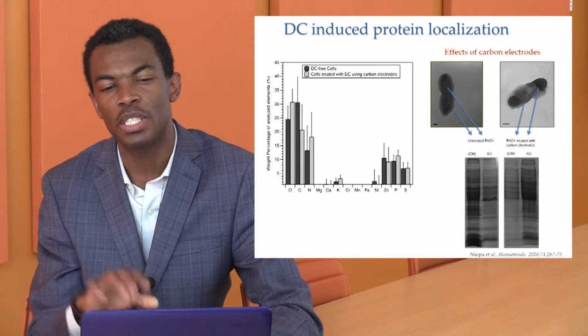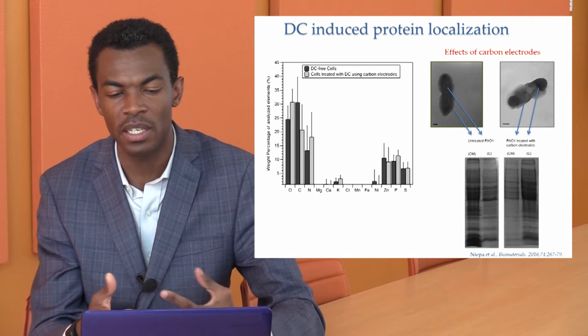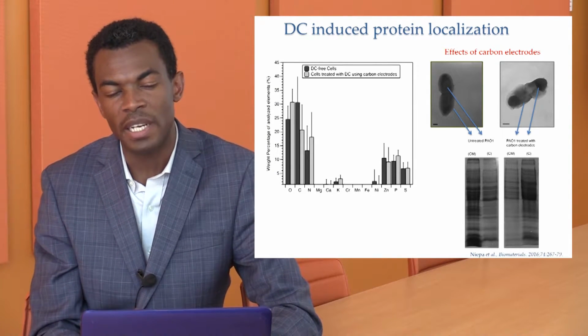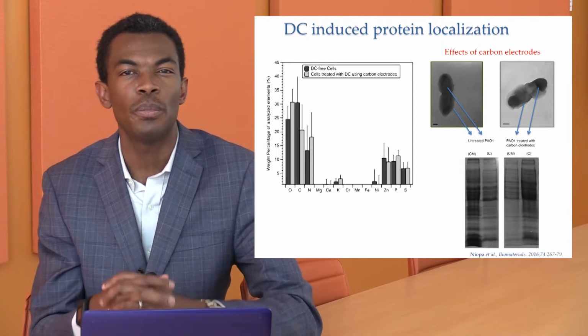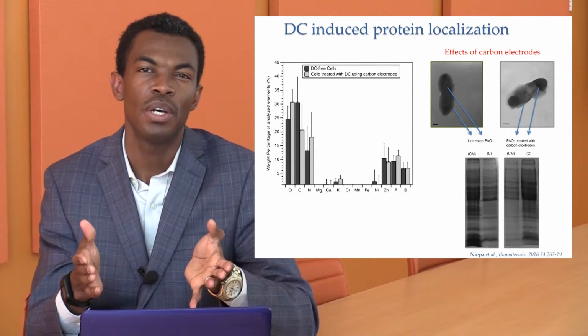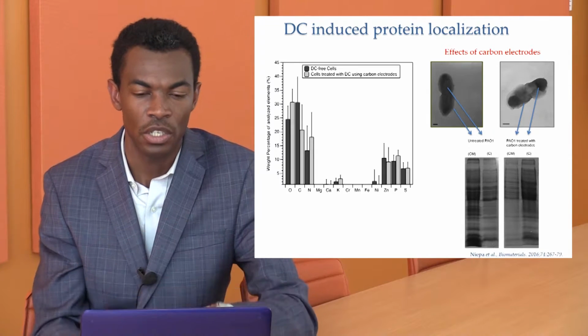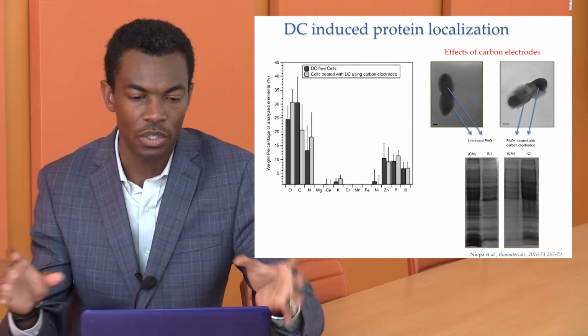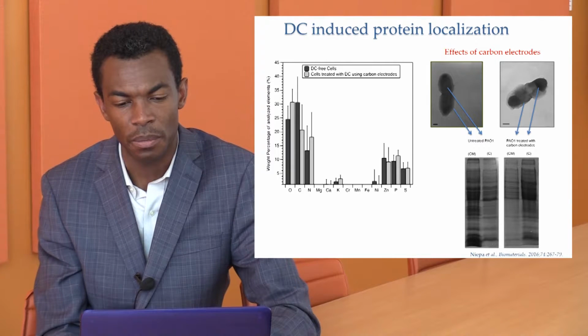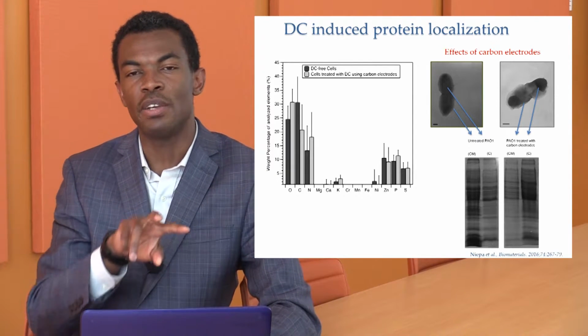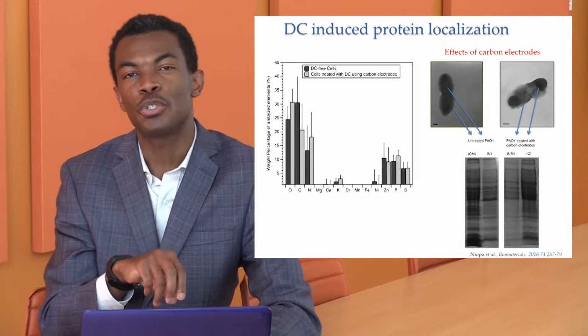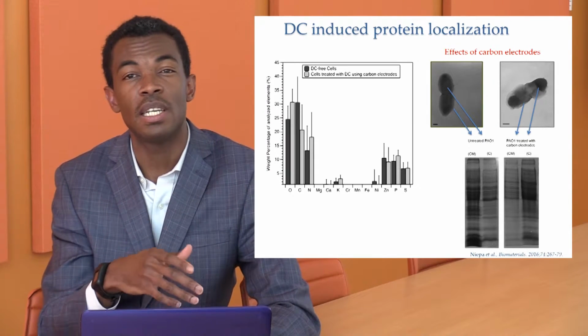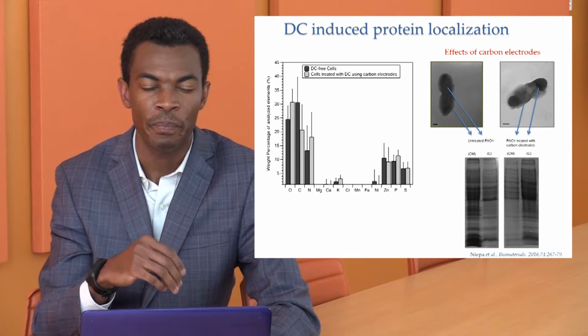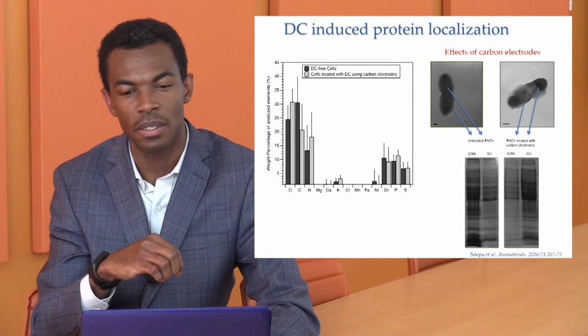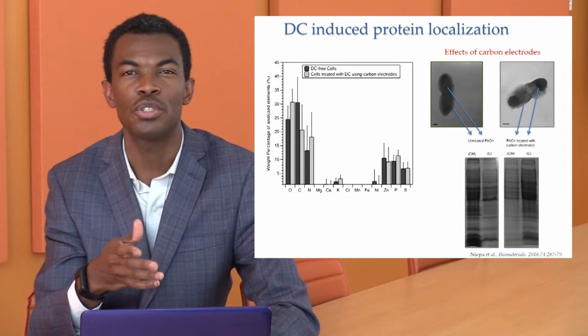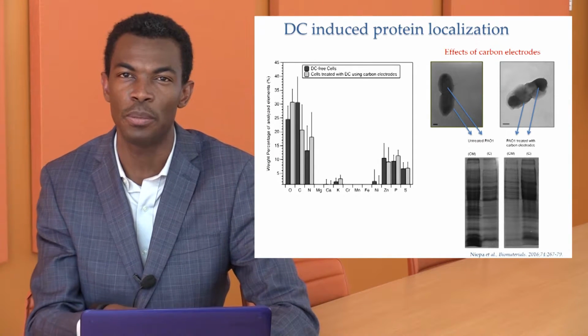So we're trying to confirm this fact, and we did perform some analysis just by quantifying the number of proteins that the cells have on the cell membrane compared to the inside, in both conditions, the control versus the cells treated with carbon electrode. By doing that, we see a very inverse pattern. So the control cells have more proteins linked to the cell membrane, but inside there are very few proteins, because here we're dealing again with those stationary phase cells that are not very much metabolically active.